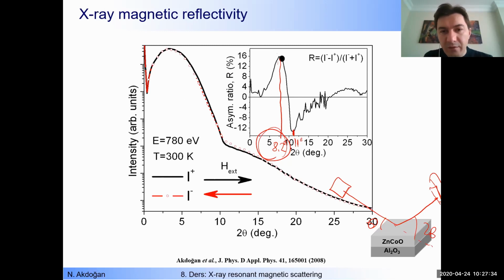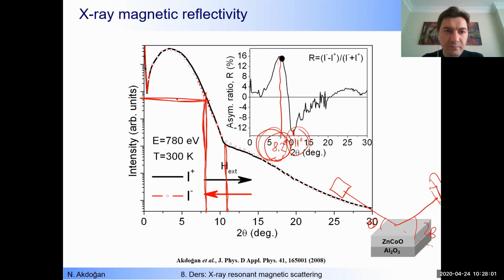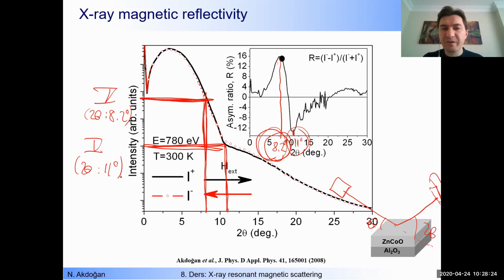Why? Let's have a look. 11 degrees somewhere here, okay, and then 8.2 degrees somewhere here. What do you see if you compare the intensities for both angles? This is the intensity recorded when the 2 theta is located at 8.2 degrees. This is the intensity recorded when the 2 theta is 11 degrees. You see, the intensity is more or less 2 times higher compared to that angle. And here we have huge difference in terms of magnetization. Then we prefer that position.